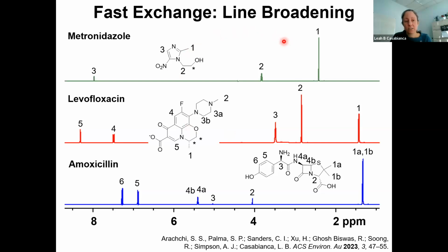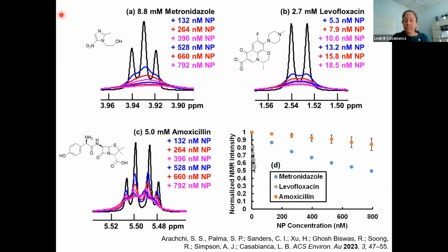We've looked at these three antibiotics as a model for small molecules that may be present in polluted waterways that might interact with nanoscale plastics. And we see that in the absence of nanoparticles, they all have very nice, sharp NMR lines. When we add polystyrene nanoparticles, though, we see a signal intensity decrease as well as